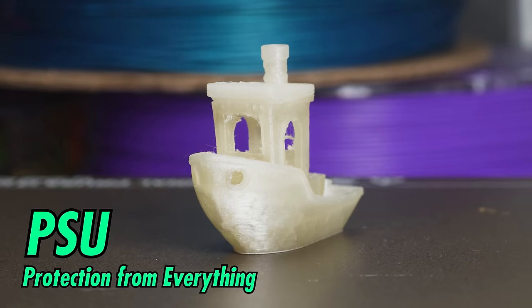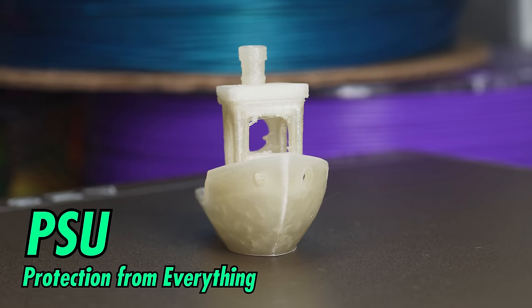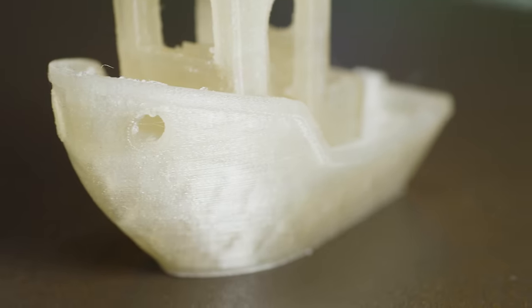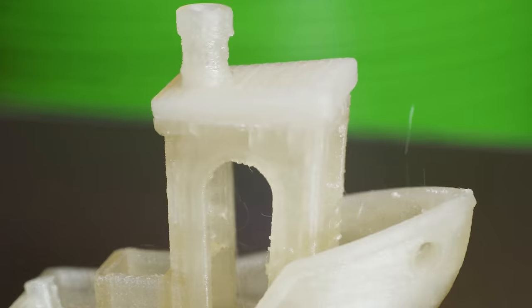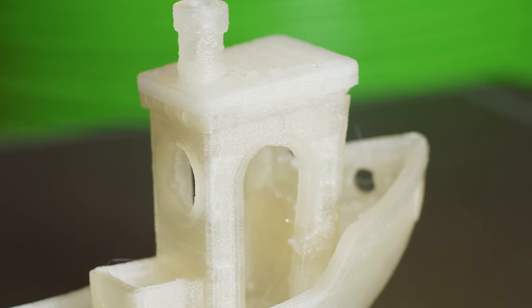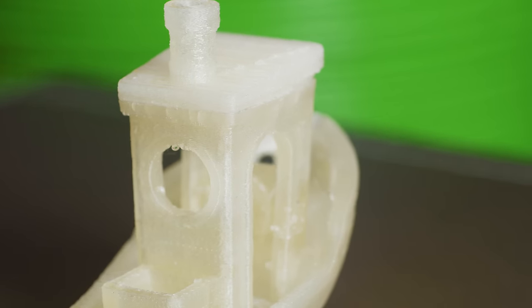So what if your print doesn't have to be unbreakable, but you do want it to be un-everything-else-able? Then the material you're looking for is PSU — polysulfone. This stuff isn't quite as strong as PEKK, although it's still extremely strong, and it's not as easy to print, but it's still fairly easy. PSU excels in harsh environments: it can resist automotive fluids even at boiling temperatures. Its glass transition temperature is above 190°C before annealing, and it withstands radiation better than almost any other polymer. This gives you the perfect material for anything that has to be sterilized, autoclaved, or fired into space.